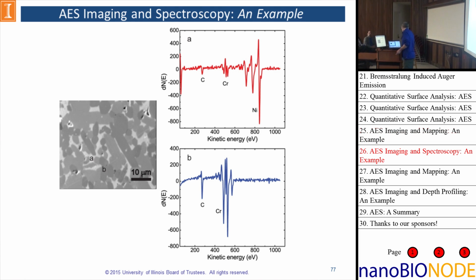Here's another example of a combination of imaging with spectroscopy. And this is a pretty simple one. We see a lot of contrast here in this SEM image. We have a light area and a darker area. And because we can move the electron probe around, we can look at a section we'll call A, which is very nickel rich, and B, the darker area, very chromium rich.